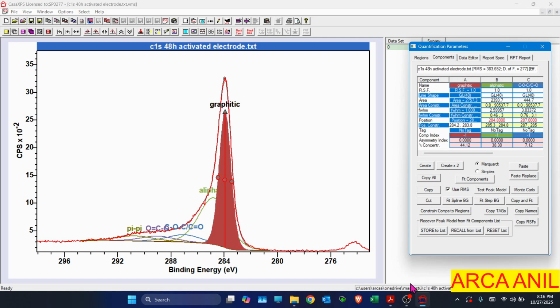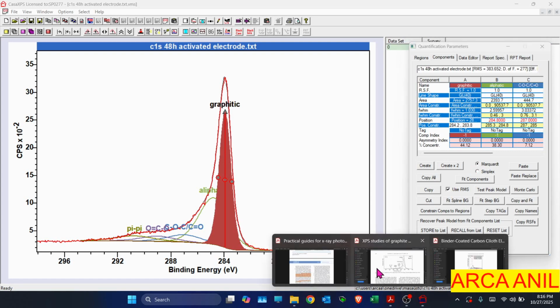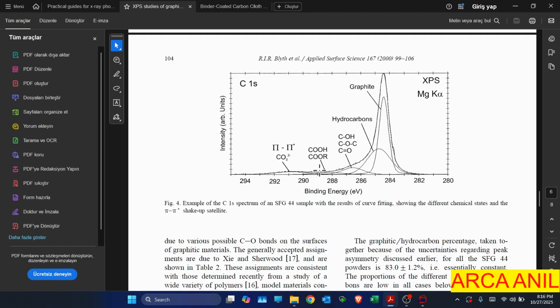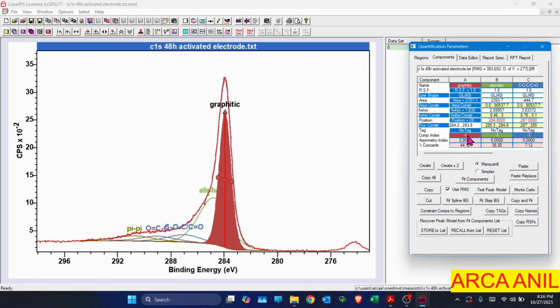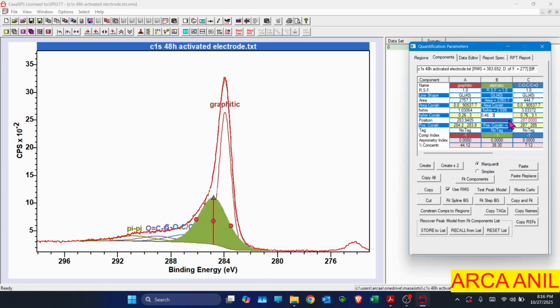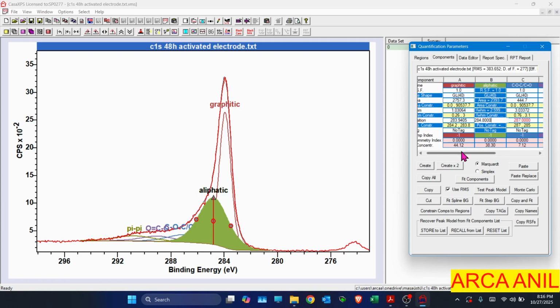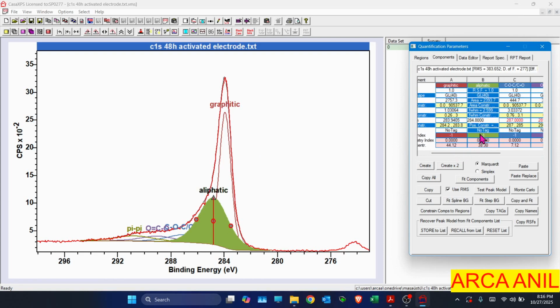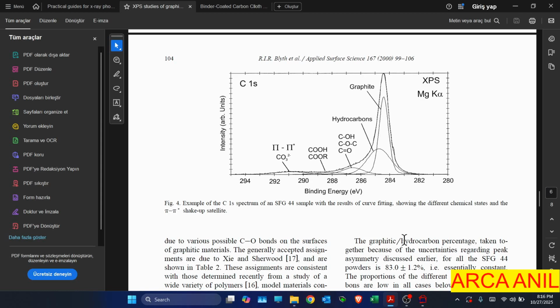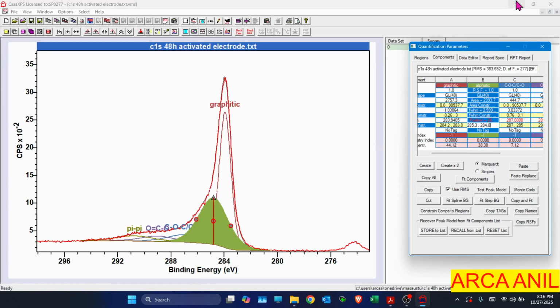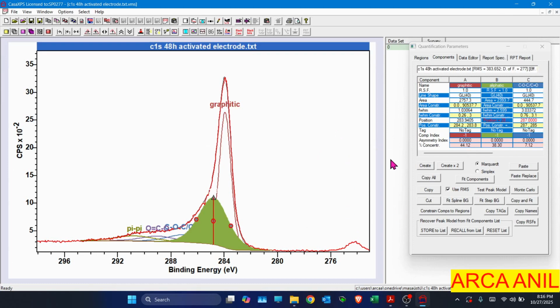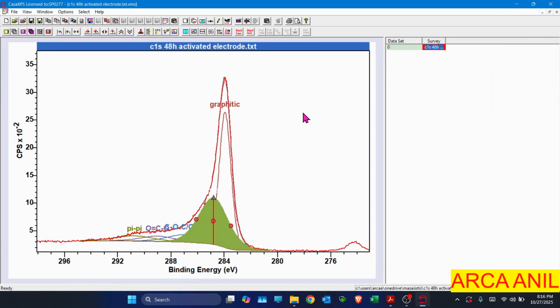And this is the case, and I can also look at the other sample data. So I think it seems good enough, and this is our peak fitting. By the way, maybe we should check the positions again. Maybe their sample has a little bit of charging. Of course, it is also another thing to consider, but it's also an electrode. But this is what it is, and I think this is good enough to make a publication.